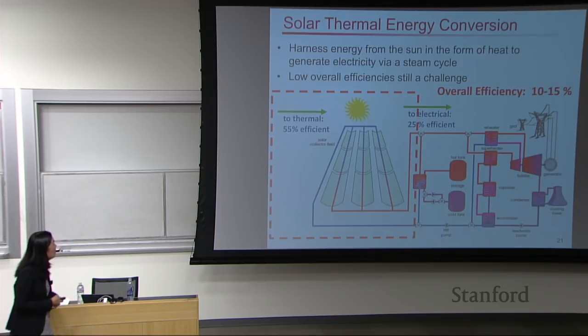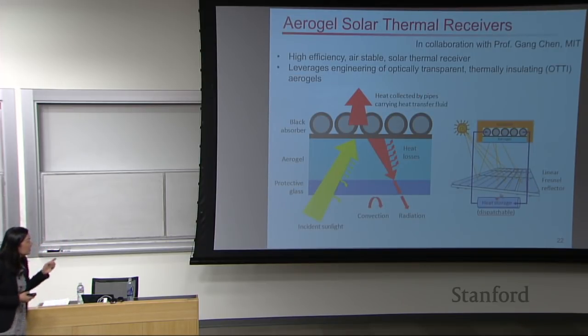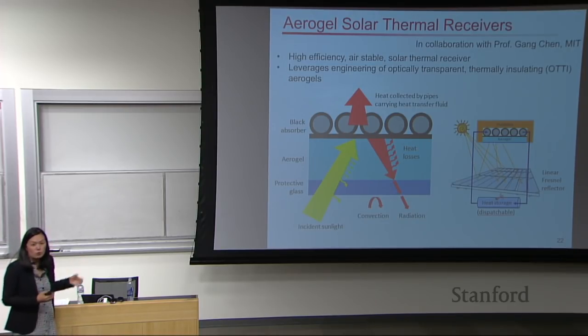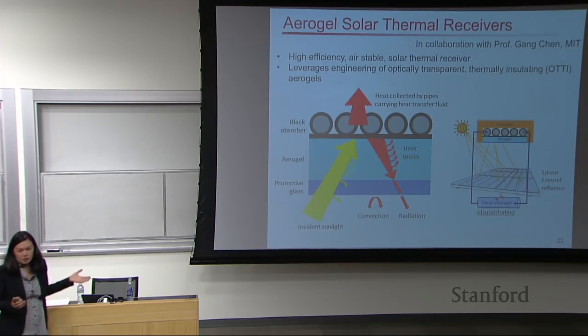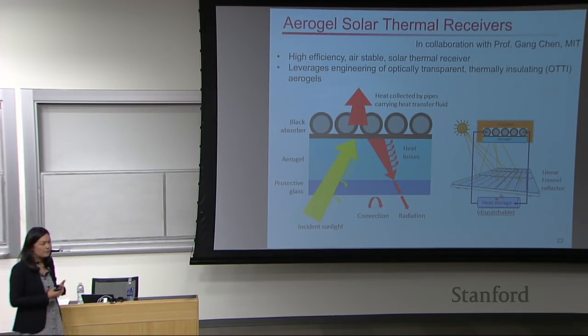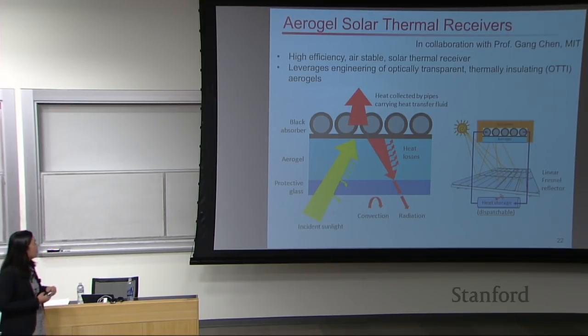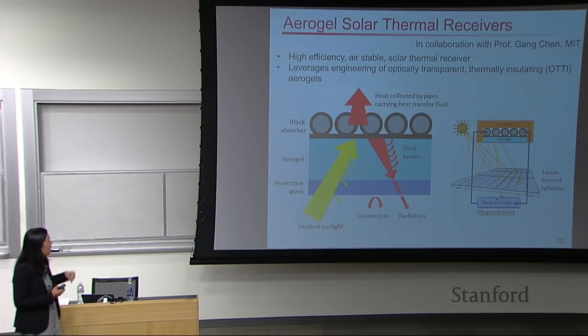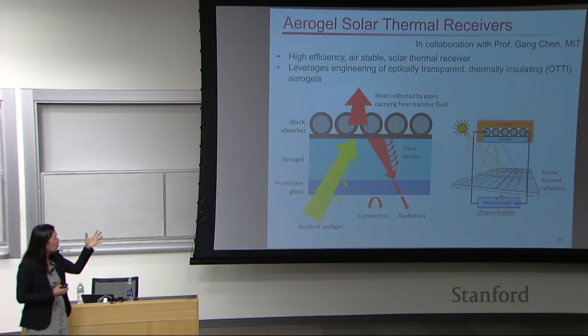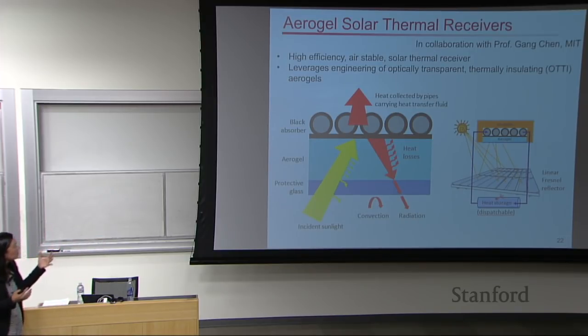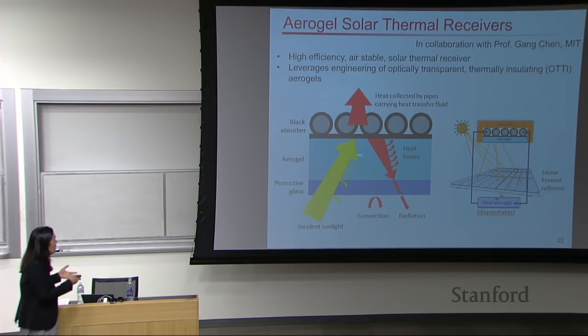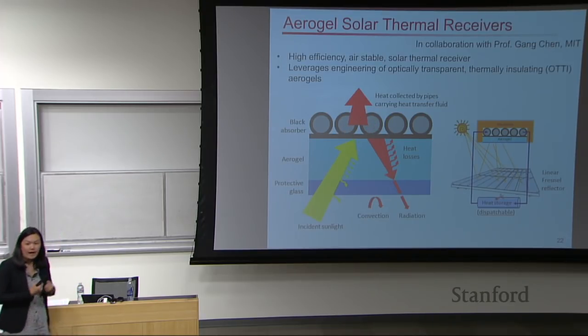complexities in the system. So one of the things that we've been working on, and this is in collaboration with Gang Chen's group at MIT, has been looking at what we call these aerogel solar thermal receivers. And the idea with the aerogel, which is commonly used in building materials, is that they're very good insulators, right? They're very good thermal insulators in this case. And what we've conceived of is an idea by which instead of just using the insulating properties of these aerogels, we also wanted to make them optically transparent, such that sunlight can penetrate into this receiver design, into these black tubes that can effectively capture the heat.